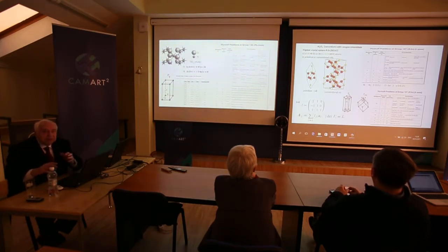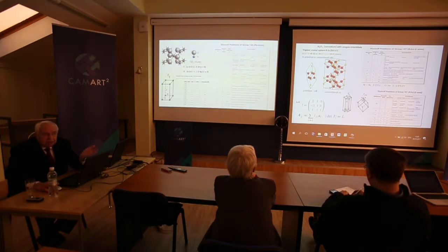But as I already told, for some groups there are two different origin choices, and for rhombohedral groups you have hexagonal and rhombohedral settings. And coordinates depend on the setting. And in databases you can find both settings, or one of them. And you need to understand what the setting is.